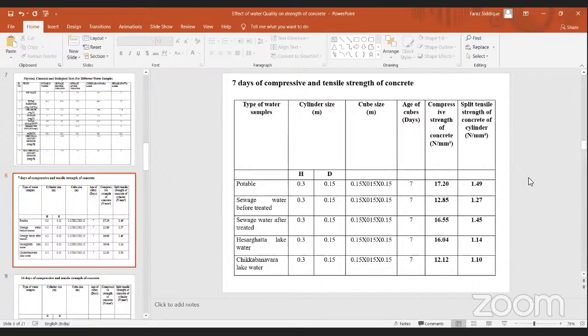And these are the results we obtained for 7 days. As I mentioned at the start of my presentation, my concrete was designed for 25 Newton per mm square, that is M25. My target mean strength was somewhere around 31.6, as my standard deviation is 4 for M25 grade of concrete. So this was the compressive strength we achieved for potable water.